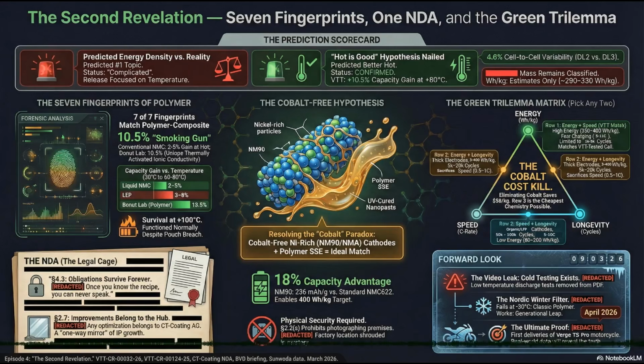At 20 degrees Celsius, which is standard room temperature, the cell delivered just under 25 amp hours. But then they bumped the climate chamber up to 80 degrees Celsius, let the cell soak in that heat so it was completely thermally saturated, and ran the discharge again. The cell delivered about 2.5 extra amp hours, settling right around 27.5. Yeah. That is a 10.5% capacity increase simply from heating the cell.